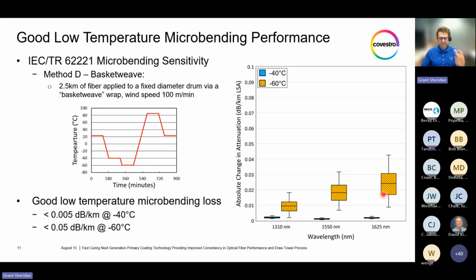However, this data is still well below the 0.05 threshold, with an average of about 0.025 at the longest wavelength, 1625 nanometers and negative 60 degrees Celsius, providing great low temperature microbending performance. Now, the increase from negative 40 to negative 60 degrees C is well understood as the primary coating approaches its glass transition temperature and undergoes a transition from a rubbery network to a more glassy network, increasing the microbending there. But overall, very good low temperature microbending performance seen all the way down to negative 60 degrees C.